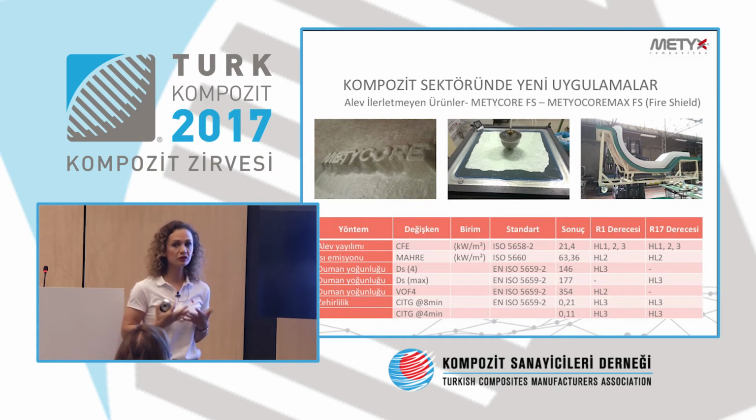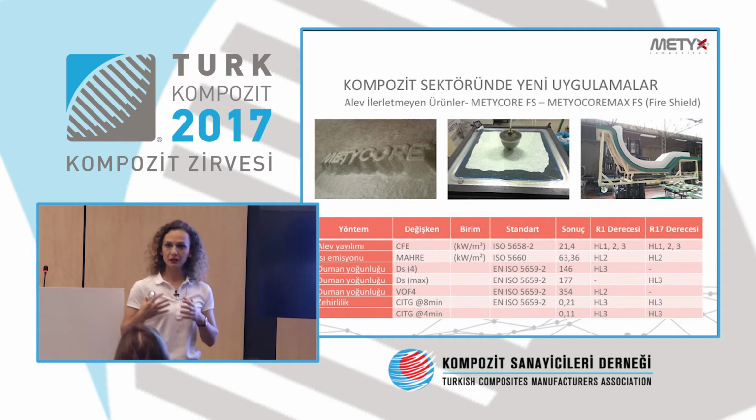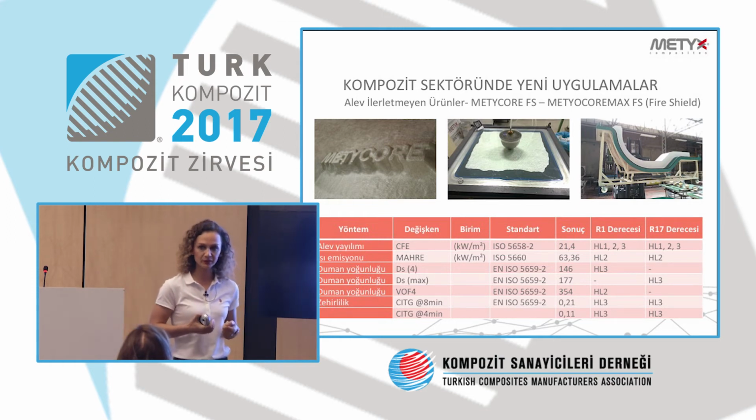Of course, one of the most important parameters is the resin itself. The resin has to be non-conductive towards fire, so the resin manufacturers are working on it, gel coat as well. So the material over the gel coat should also be non-conductive. But the resins bring up some challenges during production, because of the filling inside it, the viscosity is very high, and it is not easy to wet the fabric. There are some studies ongoing about it, but mechanically, for instance, the mats and felts have been used. However, they are not giving the necessary performance.